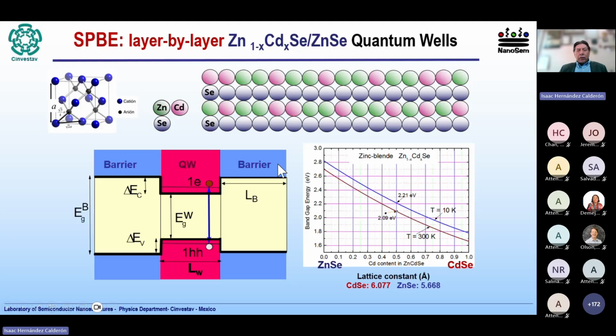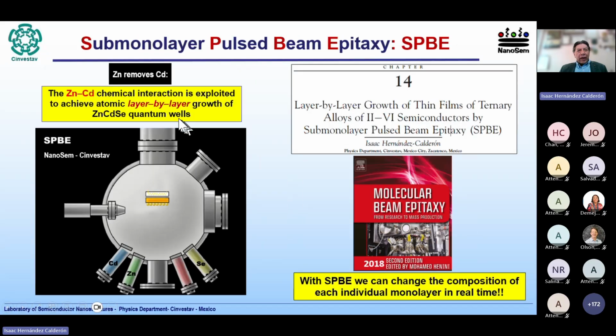But fortunately, we use the chemical properties of zinc and cadmium, because zinc and cadmium compete in being attached to selenium atoms. So the chemical competition between cadmium and zinc makes zinc remove cadmium atoms. If zinc removes cadmium atoms, we can use this technique that I will show here in a movie to make the layer by layer growth of these ternary compounds. So here we can see I open the shutter in the chamber, and we grow a layer of cadmium atoms, which can be complete or incomplete, it's not saturated in this case. Then we open zinc atoms, they occupy empty spaces or even remove cadmium atoms.